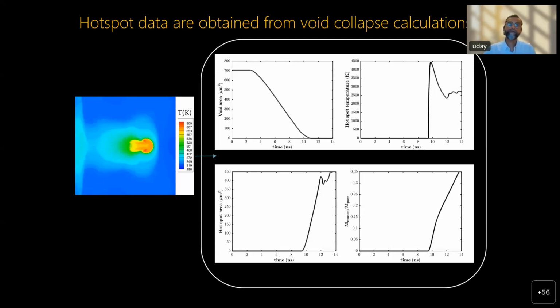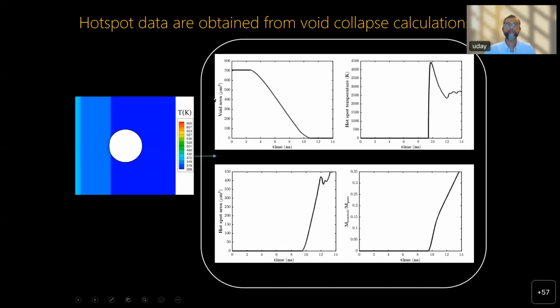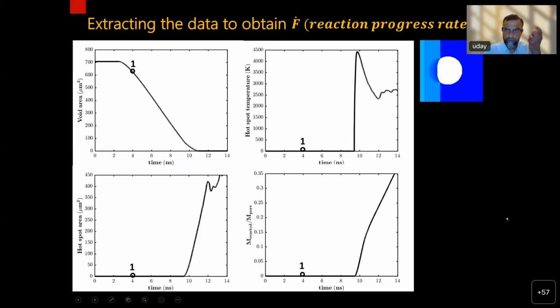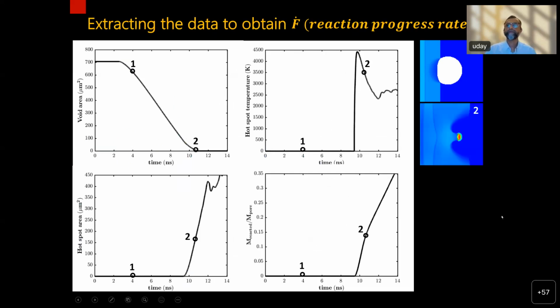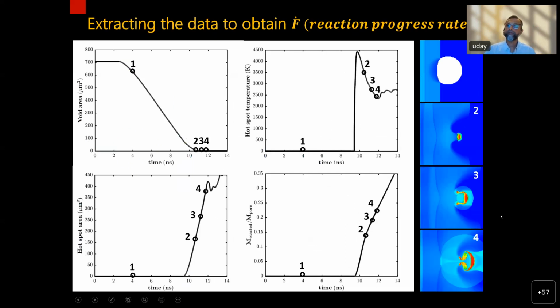Now, these are again based on the single pore data. We do the reactive pore collapse calculations. We collect data on the void collapse, the hotspot temperature, the hotspot area, and the mass fraction of reacted material that comes out of one pore. Using that data, we extract these quantities, the F dot ignition and F dot growth. These are taken simply from the data, and we calculate the slopes of the mass fraction reacted curve. From that curve we determine the F dot ignition, which is the rate of ignition due to a particular hotspot, and then we also get the rate of growth when it settles down into the growth phase.